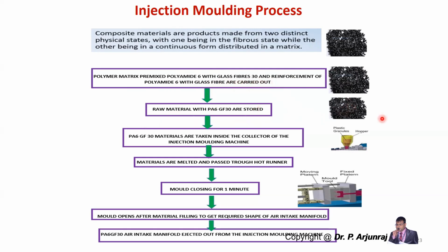Next, the raw material PA6 glass fiber 30 is stored, and the PA6 glass fiber 30 material is taken inside the collector of the injection molding machine. This is the injection molding machine, where through the hopper the material is poured inside, melted and passed through the hot runner, and when it comes out the shape is formed. The mold closing time is 1 minute, after that the mold opens and the material fills to get the required shape of the air intake manifold, and then finally the PA6 with glass fiber 30% air intake manifold is ejected from the injection molding machine. The same process is also followed for PA66 with glass fiber 30% as well.